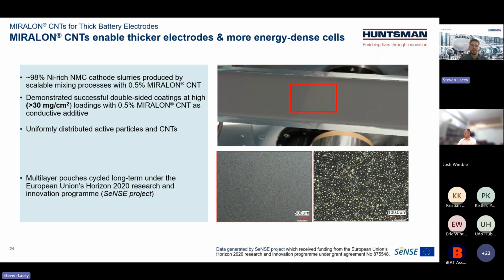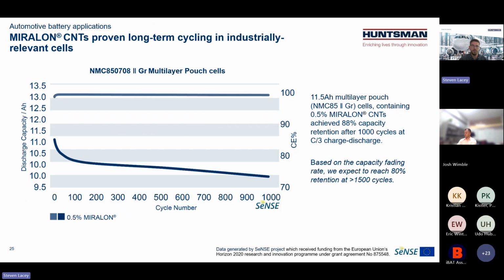And from these different pictures, you can see that the coating was very uniform, also the distribution of particles within. And from here, we took these electrodes and they were cycled in multi-layer pouches for a long term. So in this case, we have 11.5 amp hour multi-layer pouches with the 85% nickel-rich NMC versus graphite. And you can see that after 1,000 cycles at C/3, we reached 88% capacity retention.